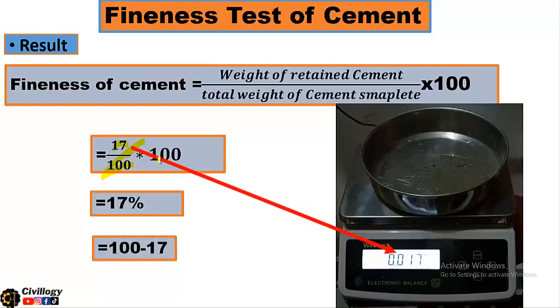As we discussed, for good quality cement this value should not in any case be greater than 10%. But in our case, as you can see over here, there are tiny residue particles. These are residue particles, because the cement bag we were using was kept open for a long time. That's why lumps formed in between, and this value exceeded 10%. So this cement quality is not good and is not recommended for use due to these lumps.